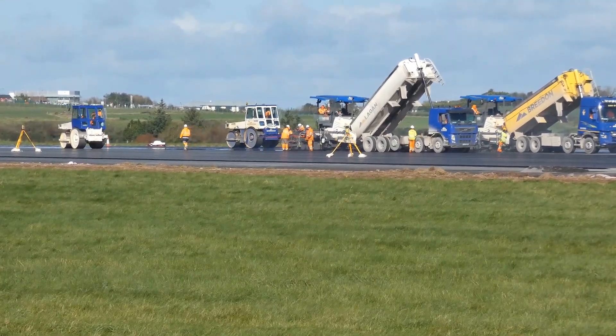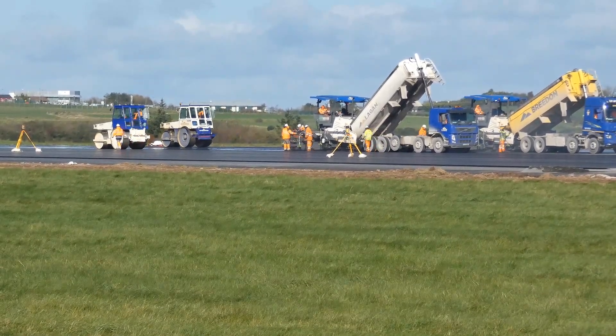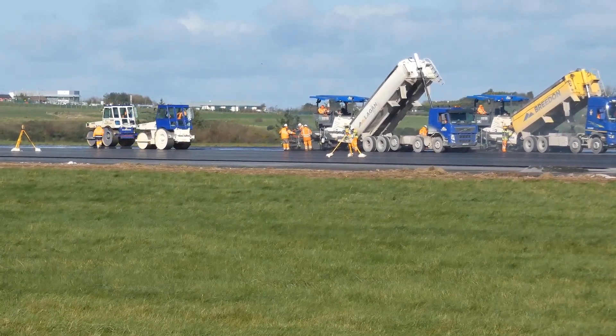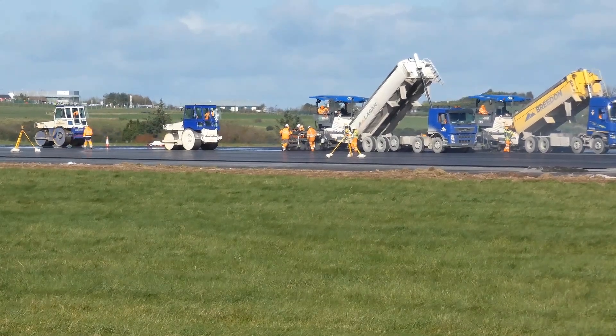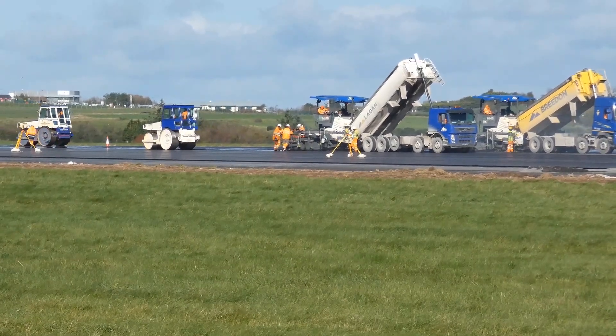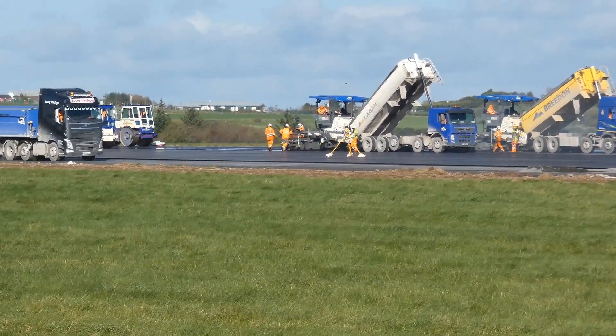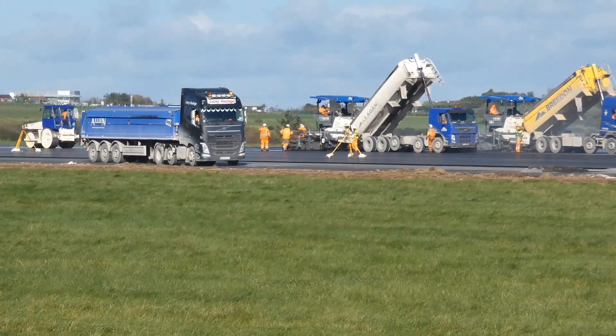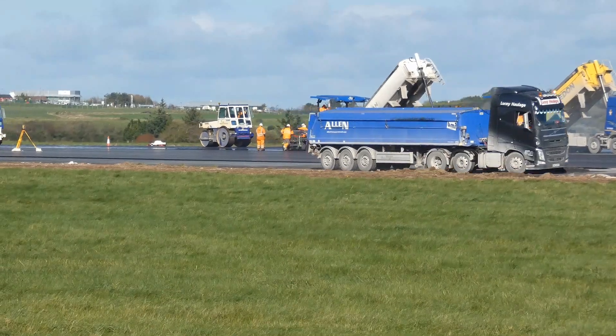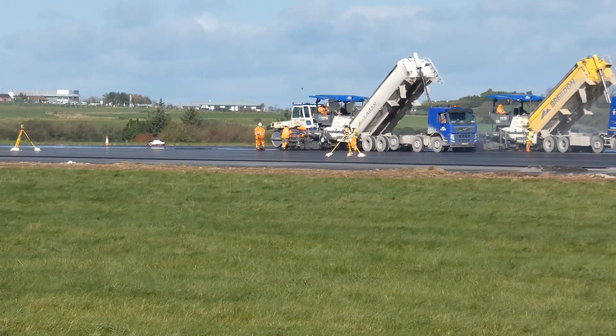Compaction of the hot asphalt mix: rollers are used to compact the asphalt to achieve maximum density and reduce the air void content. To achieve maximum compaction, the asphalt must be hot and compaction is carried out in three stages. A series of rollers operate one after another close behind the paver. The breakdown roller is the first roller behind the screed and generally achieves the most density gain of any roller in the sequence. Breakdown rollers can be of any type but are most often vibratory steel drum.